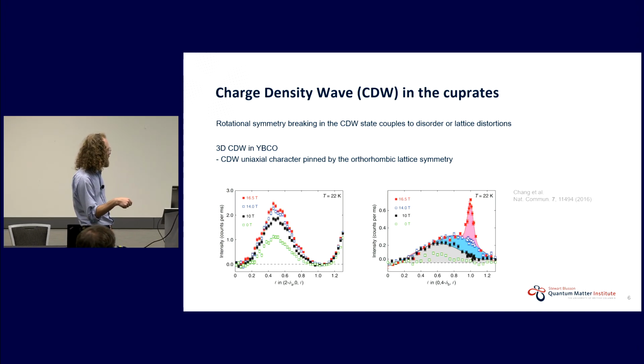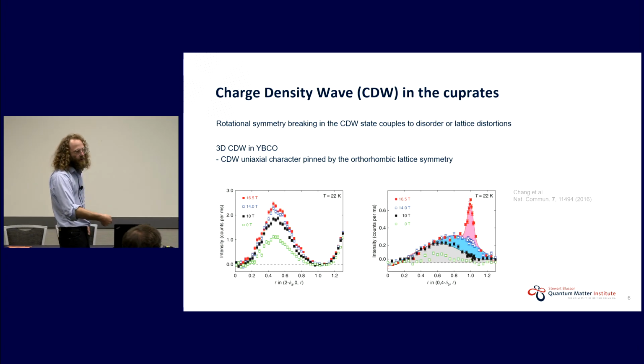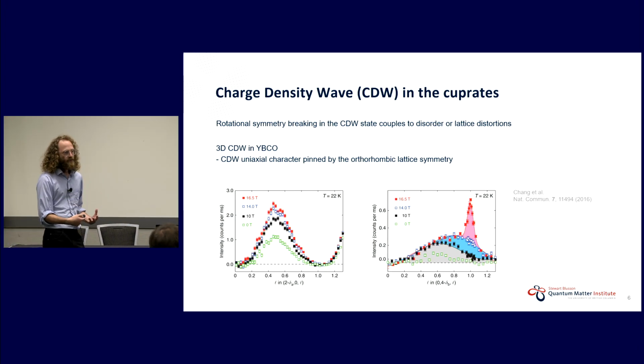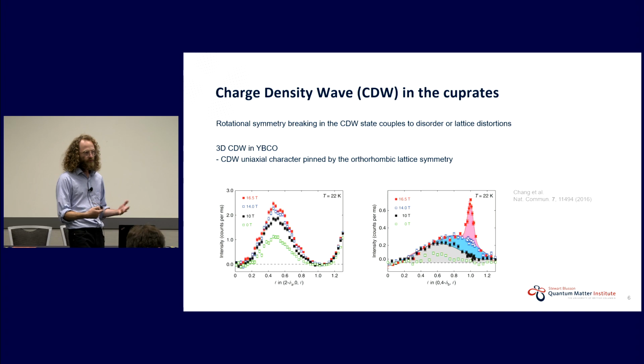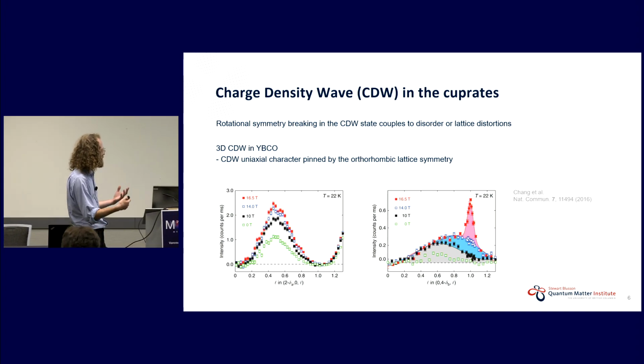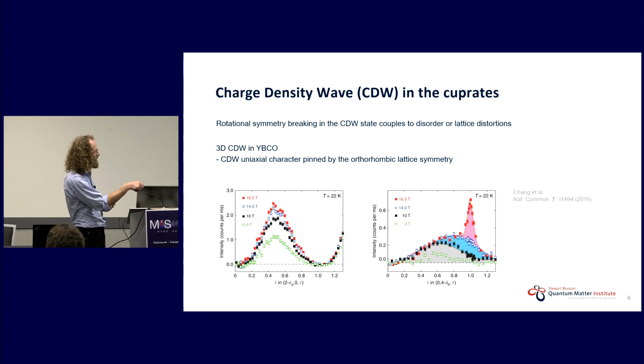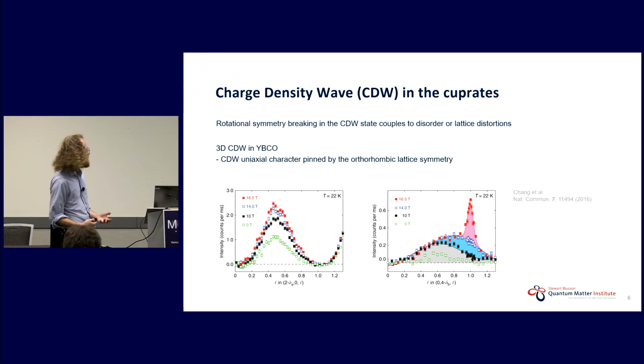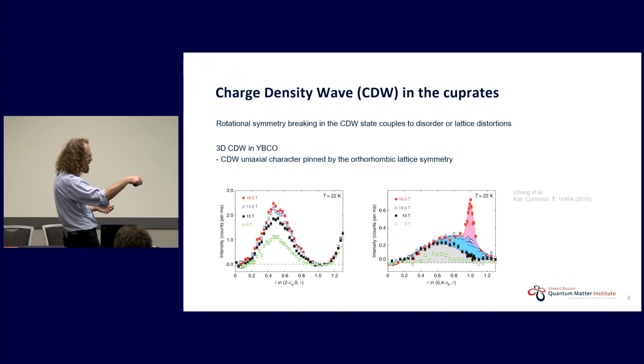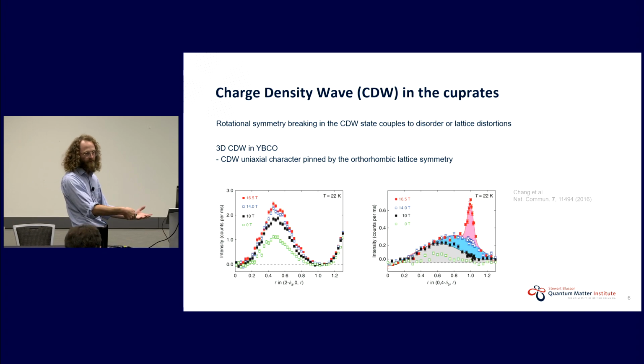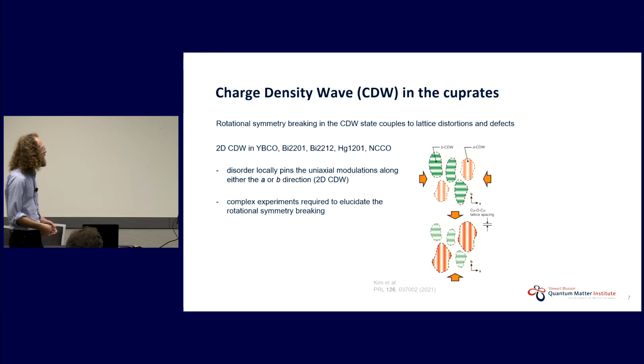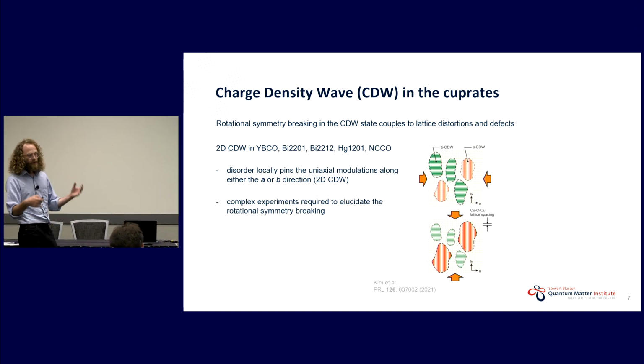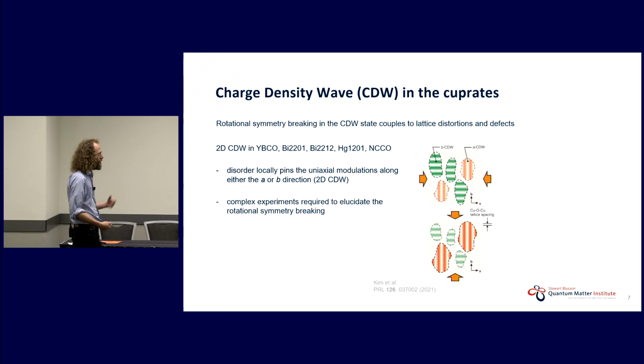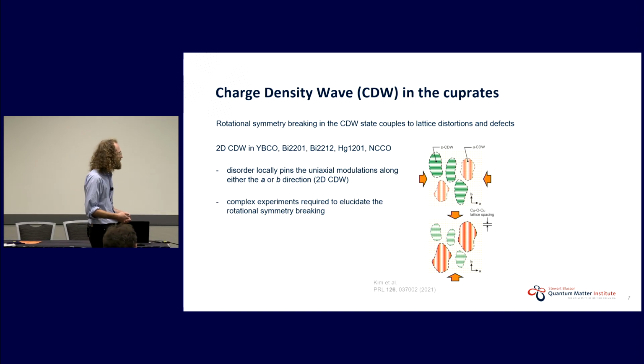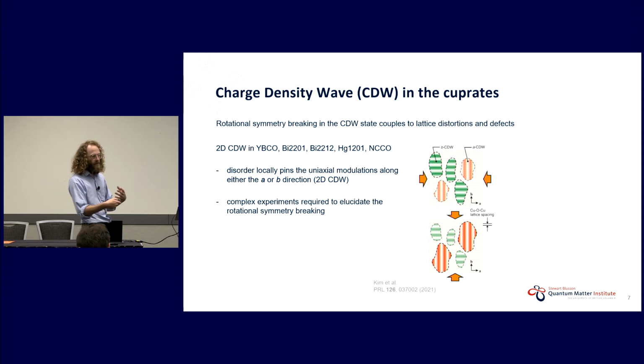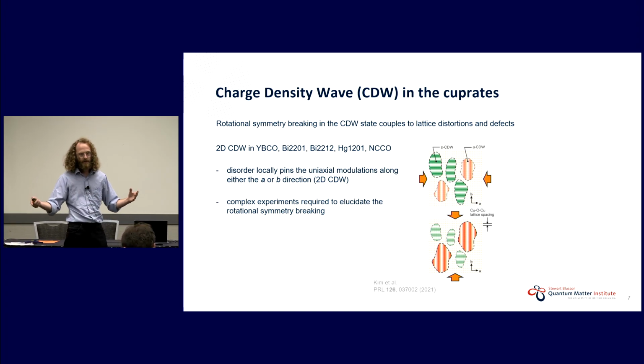Okay, so charge density wave in the cuprates, how does it fit into that sort of characterization? Well, we have a number of different examples. So typically, in the CDW in the cuprates, this rotational symmetry breaking is pinned to disorder or to some sort of structural distortions. So in the case of the 3D CDW, which you see in high fields or uniaxial strain in the cuprates, the uniaxial character is pinned to the orthorhombic B direction. It's just the lattice symmetry. In the case of the 2D CDW, the one you see in ambient conditions in YBCO, but also the bismuth-based and mercury-based cuprates, we see uniaxial CDW domains along both the A and B directions.